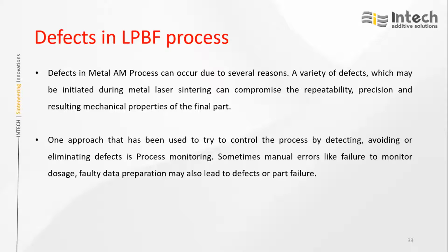One approach that has been used to control the process by detecting, avoiding, or eliminating defects is process monitoring. This is called in situ process monitoring. During the printing only, we use photodiodes or high-end cameras. We capture the images or capture the abnormalities that come during printing, and we find the solution for it.